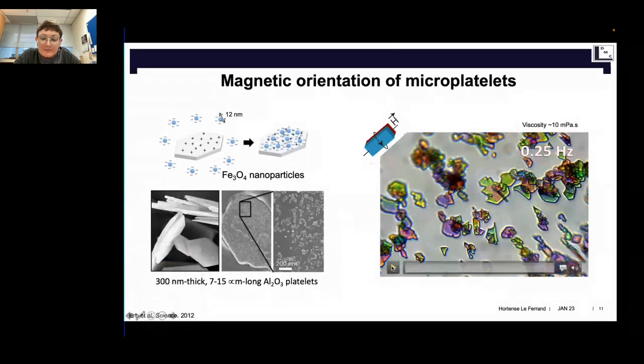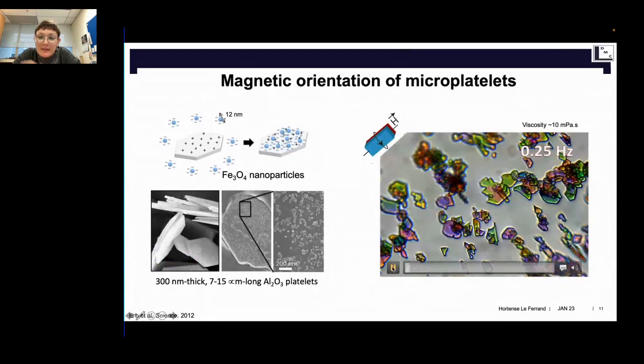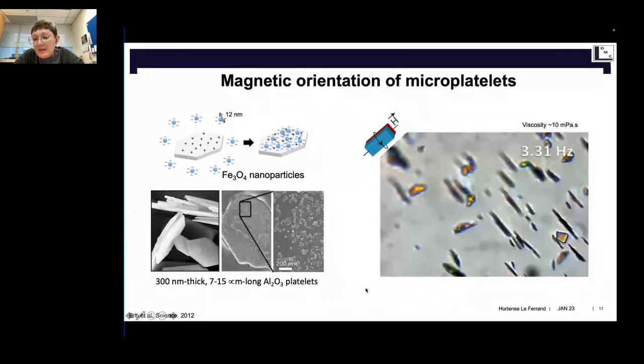So when you rotate the magnet at a small frequency, the platelets will turn. And when you increase the frequency, at some point, you see they start to align perpendicular to this axis. And you see they align parallel to each other, a little bit like in this nacre-like structure. So rotating magnetic fields at a frequency higher than 3 Hertz for particles suspended in the liquid, that's our method.